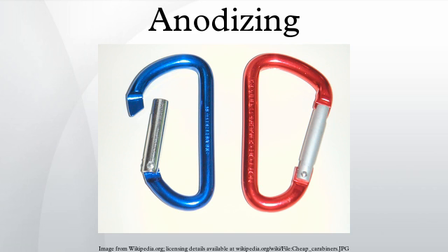Alternatively, metal can be electrolytically deposited in the pores of the anodic coating to provide colors that are more light-fast. Metal dye colors range from pale champagne to black. Bronze shades are commonly used for architectural use. Alternatively, the color may be produced integral to the film. This is done during the anodizing process using organic acids mixed with the sulfuric electrolyte and a pulsed current.